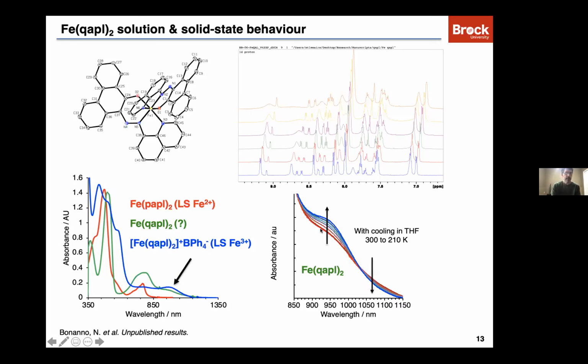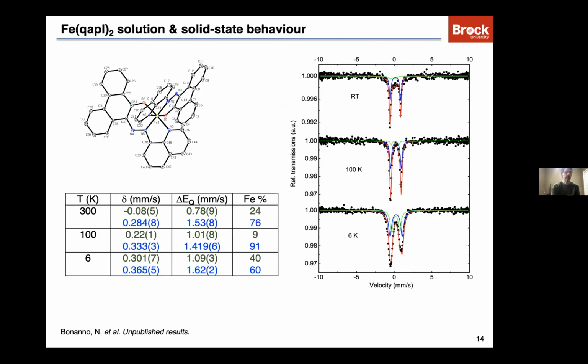And so what we think we have, again, this is a work in progress, but what we think we have here, in the green spectrum, which has this temperature dependence, the iron QAPL complex that's not oxidized, is electron transfer. So we have valence tautomerism without a change in spin state of the metal. So we're going from iron 2 to iron 3, and a QAPL anion to a QAPL dianion radical. Now, in both cases, both complexes would be diamagnetic. So we have low spin iron 2 and two anions coordinated, or low spin iron 3 with one radical, where we would have strong antiferromagnetic coupling, resulting in a diamagnetic system,